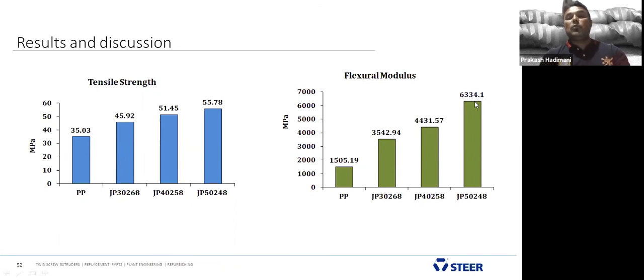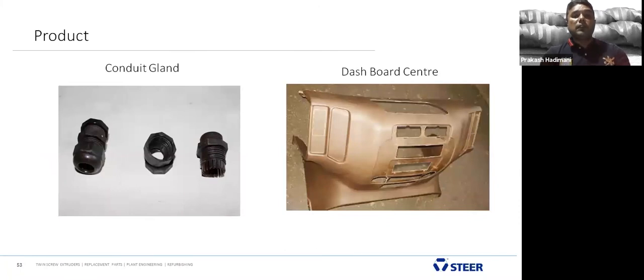And compared on flexural modulus, again the addition of jute is increasing it. You see that it almost touches the chopped glass fiber. Chopped glass fiber is also similar. If you add 20 to 30%, we are reaching 5,000 to 6,000 of flexural modulus, but the jute itself is giving better flexural modulus. These are some products we did with jute. Some dashboards and some conduit glands we did.